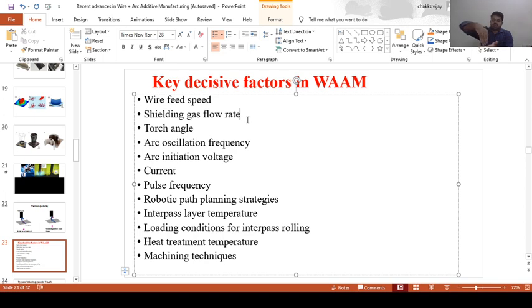For example, a 15-degree torch angle will have some specific texture. If the torch is tilted to 30 degrees, the end component will result in a different texture component, because the grain growth will be different. The grain can grow straightward or sideward or even in angular ways or some other angle. So it is completely based on the torch angle. This kind of preferential building texture could be possible, which is a hot spot of the research at present.